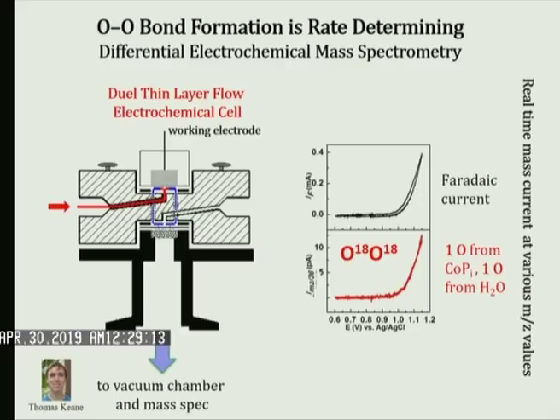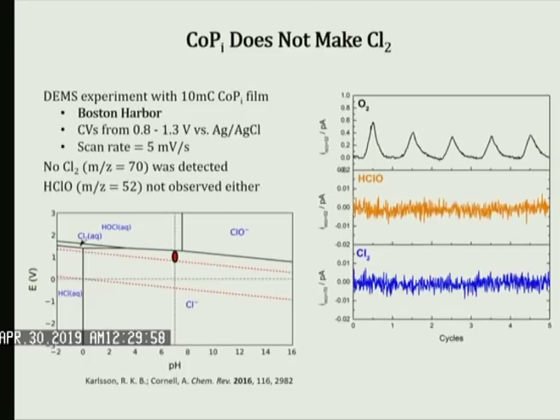So as he scans a voltage, and here I get up to 1.2 volts, I told you that's what we need to see for oxygen. Now he sees current. The current could be due to any oxidation process, but in this experiment, the mass spec is the y-axis, and it can only see the O2. So we set the mass spec, in this case we used 18O isotoped water. So my oxygen, if it's coming from the water and not from my catalyst, I should get 36O2. So Thomas puts the mass spec at m over z of 36, and that's where we see oxygen.